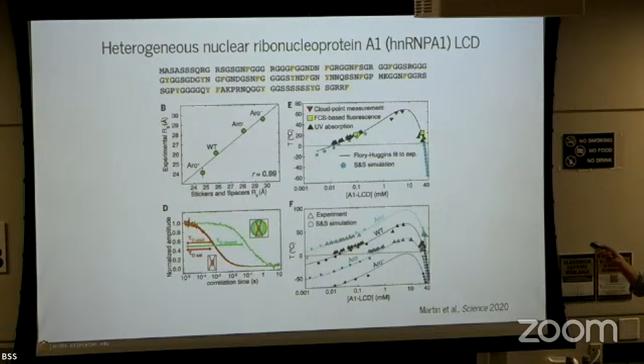And at first glance, this might be a bit surprising because our Flory model assumed homopolymers, right? But this is clearly a heteropolymeric sequence. The key idea is that if we are in this weak binding regime, then everything gets averaged out. These mean field approximations of everything being roughly uncorrelated hold up quite well. And you really can fit this effective Flory chi parameter to describe this.